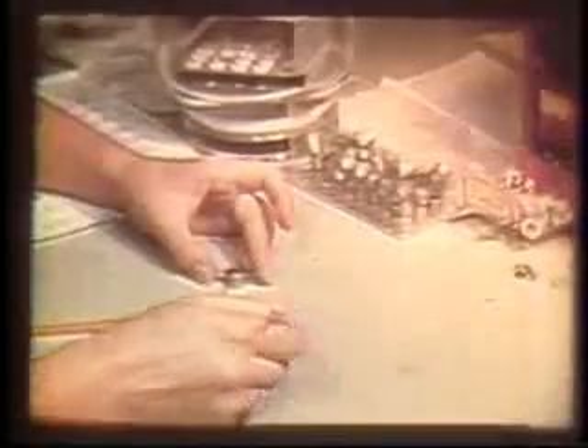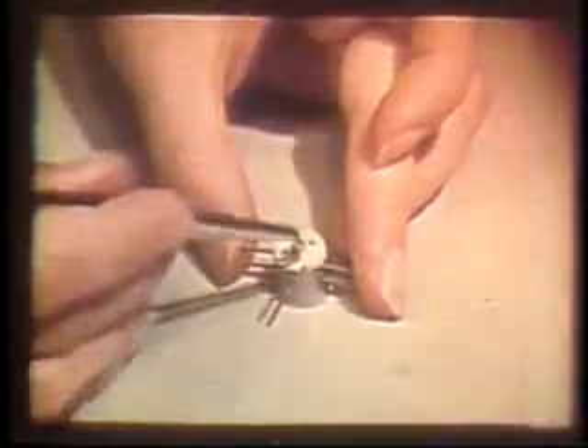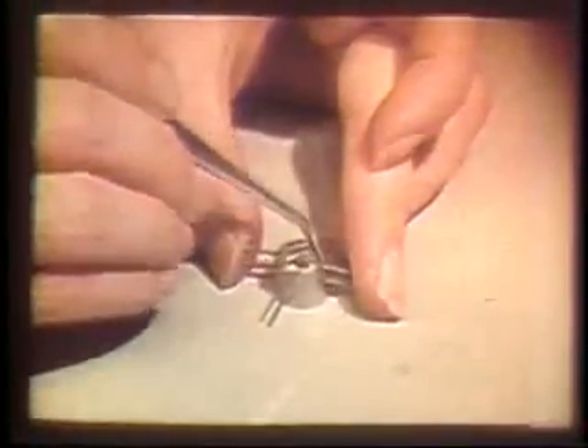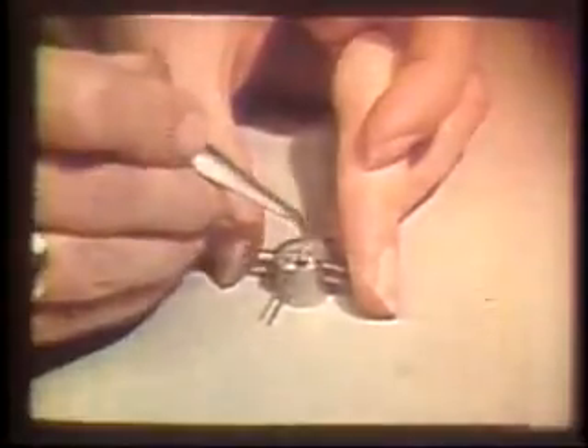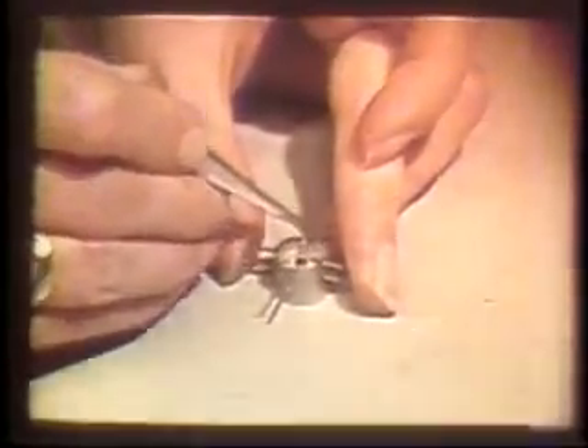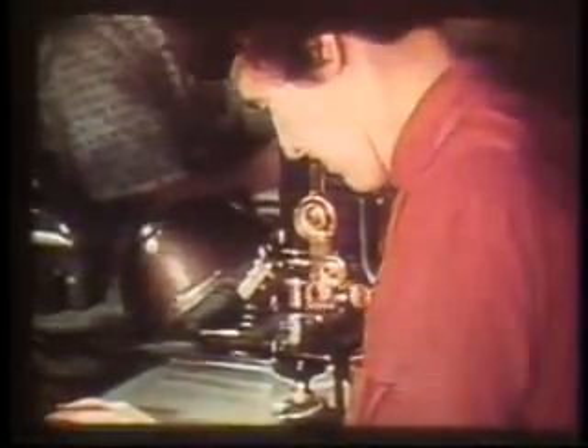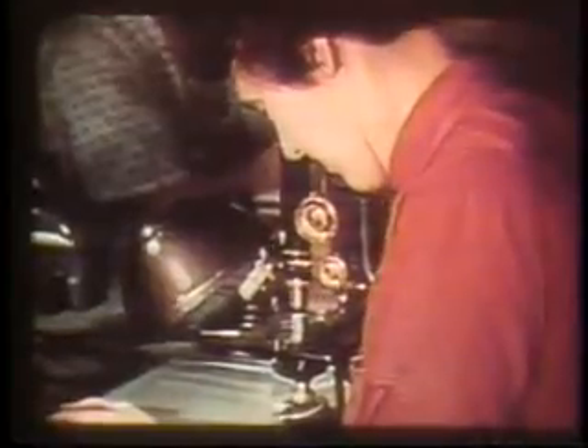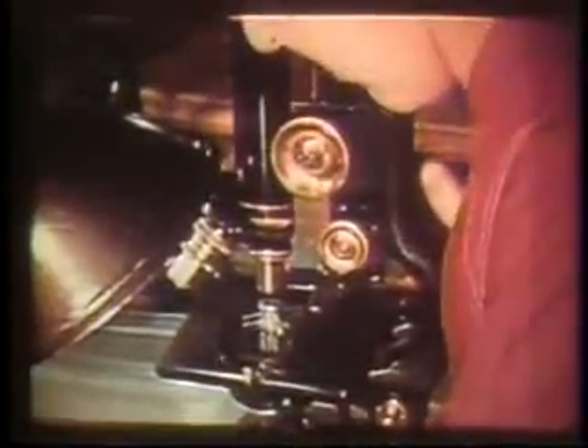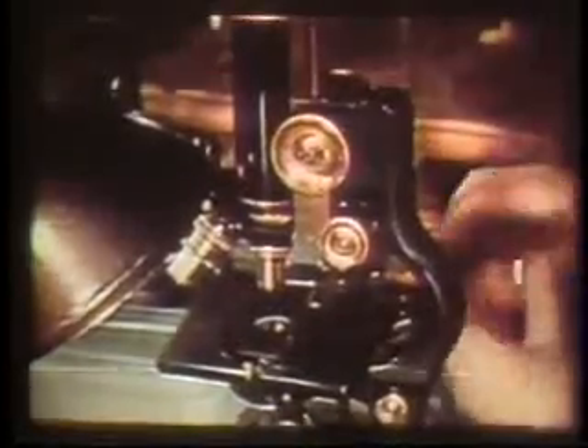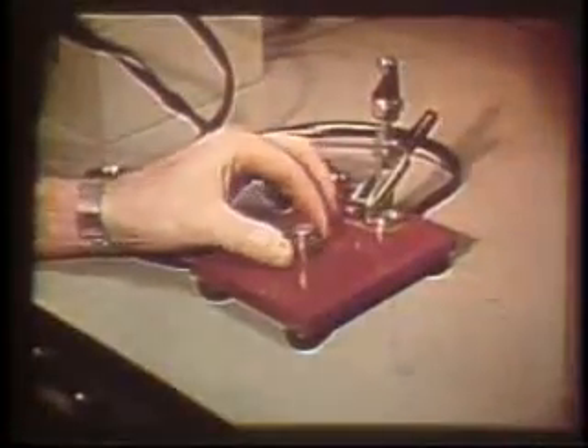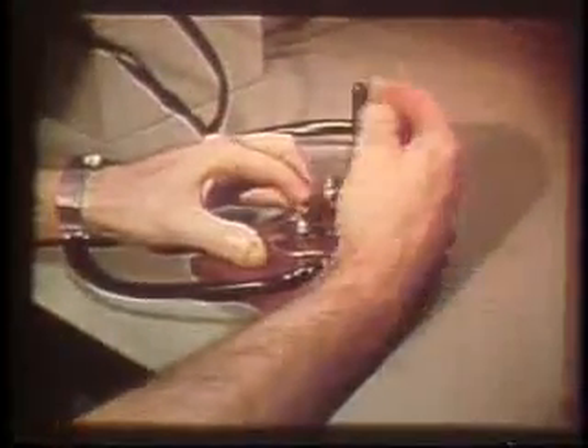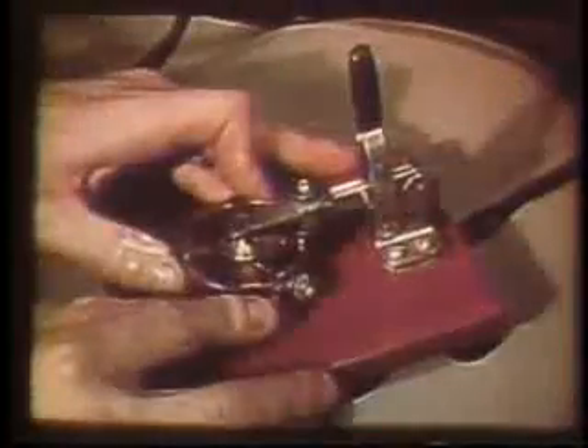The prepared cathodes are placed within the grid assembly. A retaining ring positions them in place. In order to maintain the proper grid cutoff voltage, it is necessary to hold the grid to cathode spacing to a tolerance of better than 5/10,000ths of an inch. Each assembly is measured and inspected with the aid of a microscope. The retaining ring is welded to the grid assembly, ensuring permanent alignment.